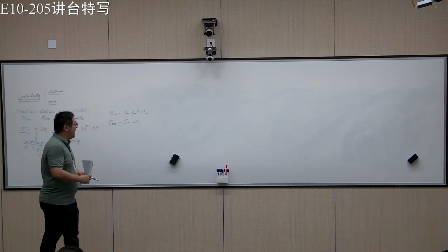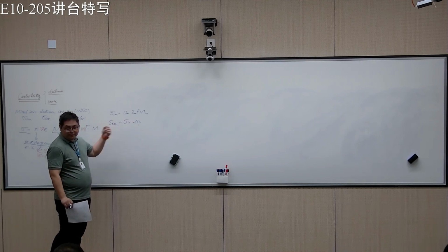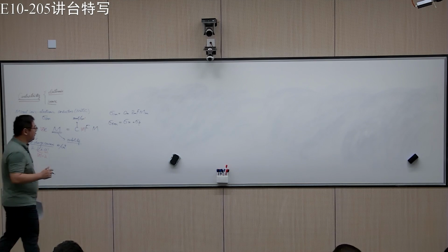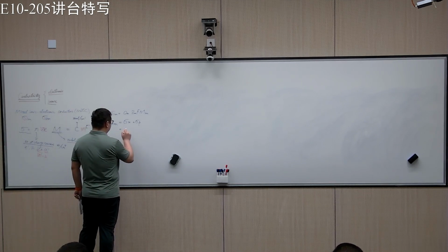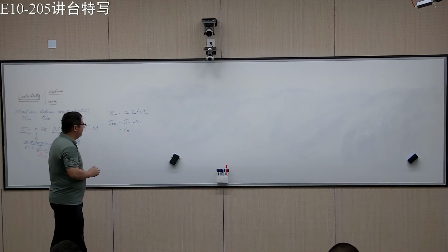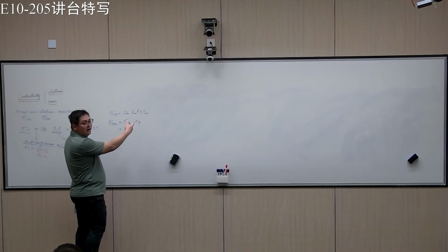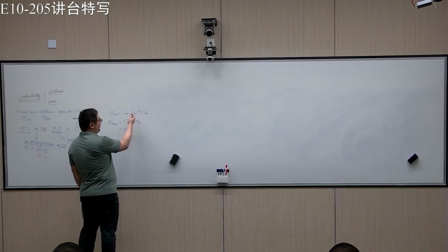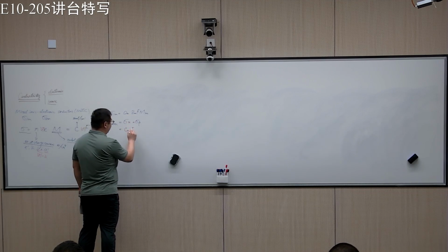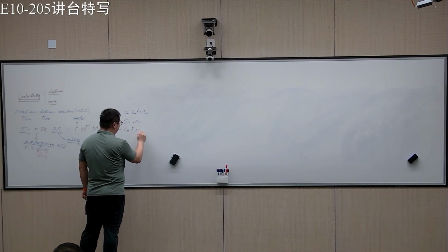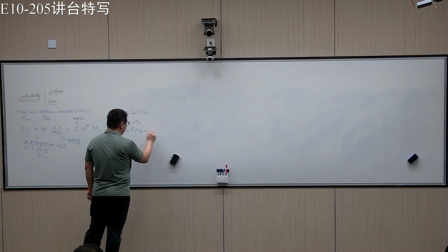You may have more electrons than holes, or more holes than electrons, but in the formal treatment, you have to sum these two. Then you have, for example, C_n, the concentration of electrons. For electrons and holes, they have only one charge, so Z is 1: C_n F mu_n plus C_p F mu_p.